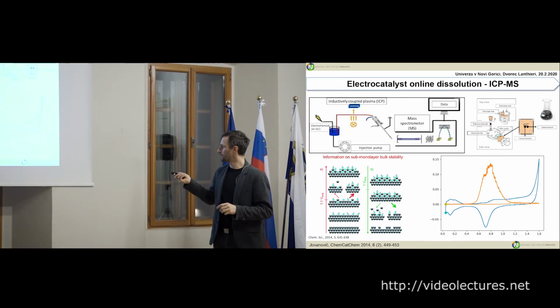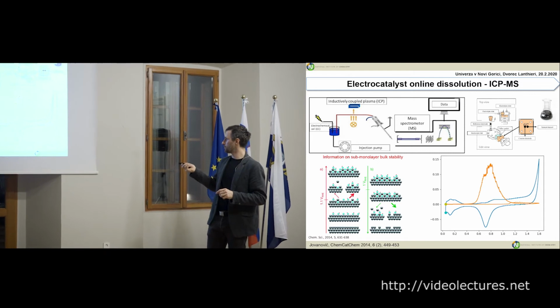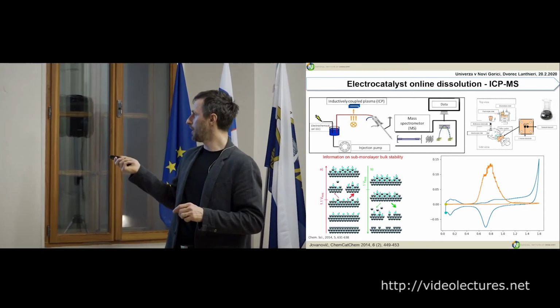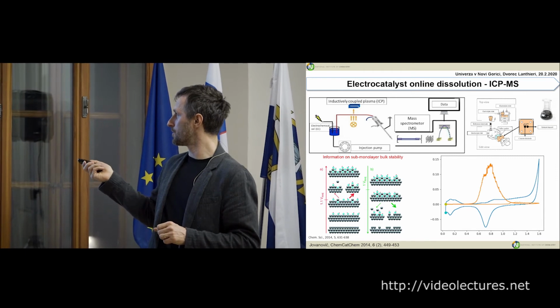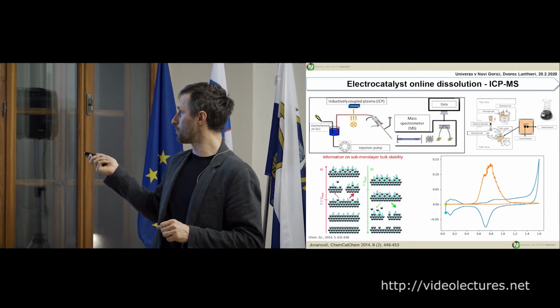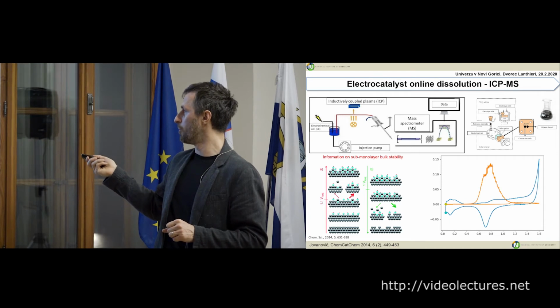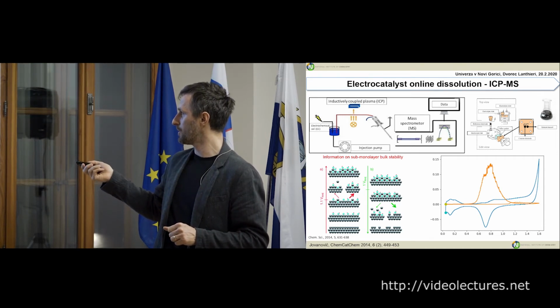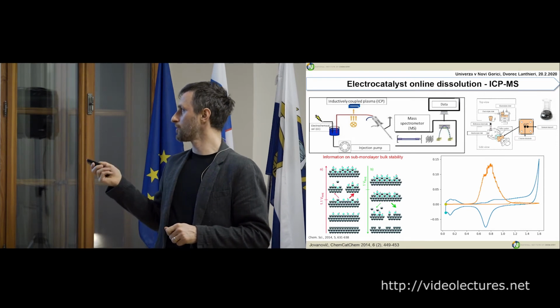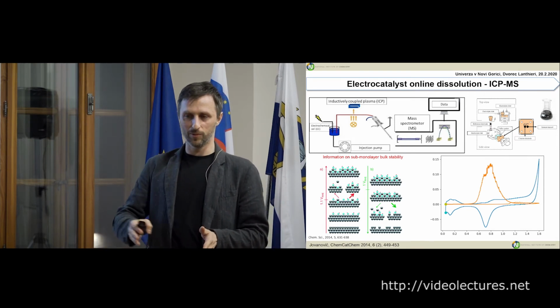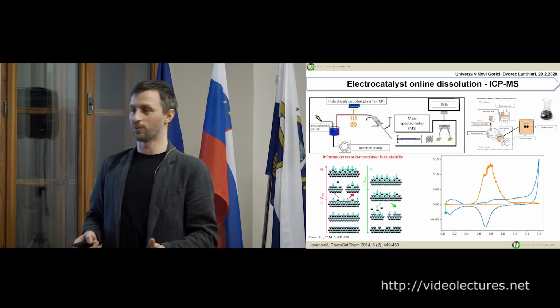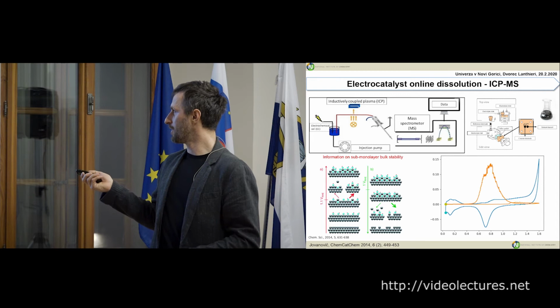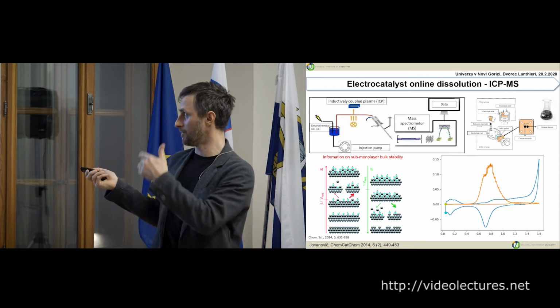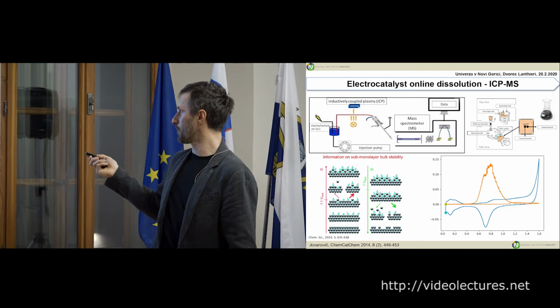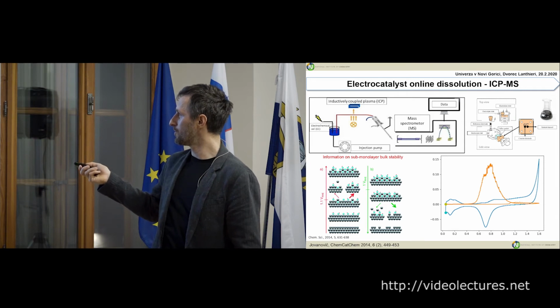So here is the cyclic voltammogram and the dissolution profile. We start here, this is the typical image, and you go up with the potential. So this is the CV, and this is the dissolution curve. You go up, you oxidize the platinum, and then you go back and you reduce the platinum. This is the reduction peak, and this is the dissolution. What's interesting here is that platinum is dissolving when you're reducing it, which is counterintuitive. It's really nicely seen because of this setup. So you oxidize the platinum, here you go to some oxygen evolution. Then you go negative, and when you reduce, you dissolve platinum.